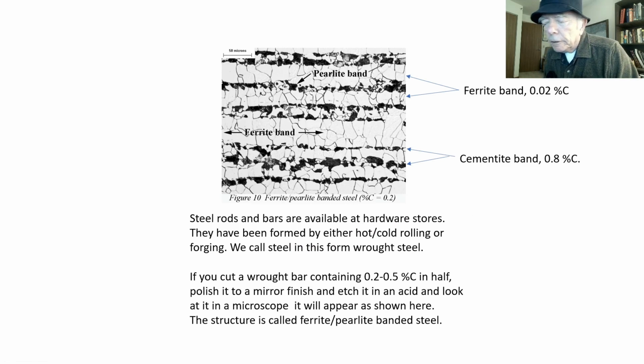Now I want to show you something interesting that led me to my hypothesis. Go to a hardware store and purchase a small bar of steel. It'll usually have a composition in this range, 0.2 or so. We call such steel that's been heavily transformed by rolling or forging wrought steel. Now, if you cut a wrought bar containing these low levels of carbon in half, polish it to a mirror finish, etch it with nital, and look at it in a microscope, bingo, that's what you see.